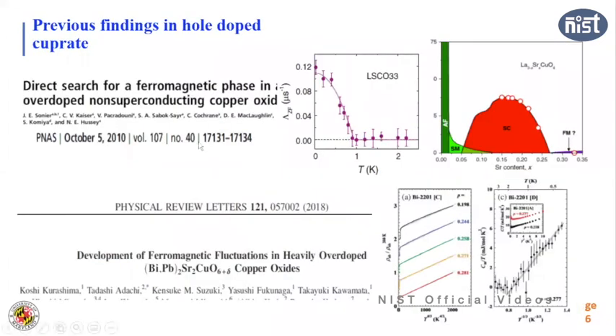There are other findings as well. In a hole-doped superconductor in 2010, this LSCO also shows there is possible ferromagnetism, but there's a question mark here because the study they did was a mu-SR measurement. Mu-SR doesn't distinguish between antiferromagnetism and ferromagnetism. And based on the theoretical prediction, they thought most likely there is ferromagnetism beyond the superconducting dome.